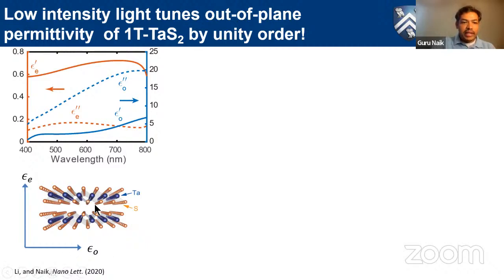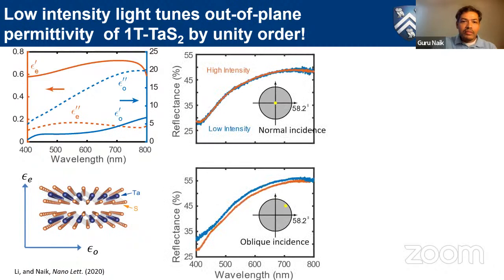It's a uniaxial material, so in the plane I have one particular permittivity and out of plane another. So I have both of them, the real and imaginary parts, shown here. It's not really very interesting because it's just an absorbing dielectric. Nothing special, at least at low intensities. But what is special is the intensity dependence of these optical constants.